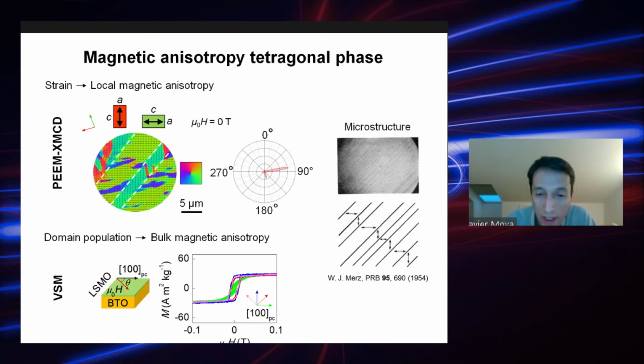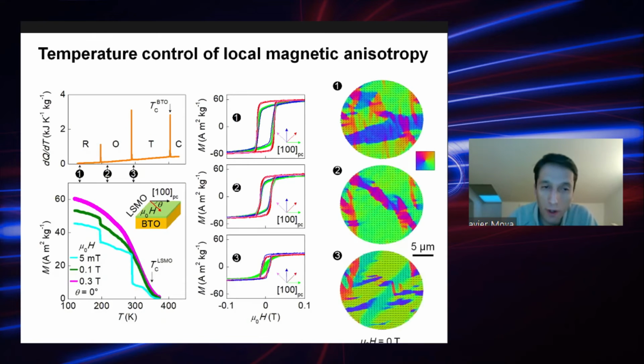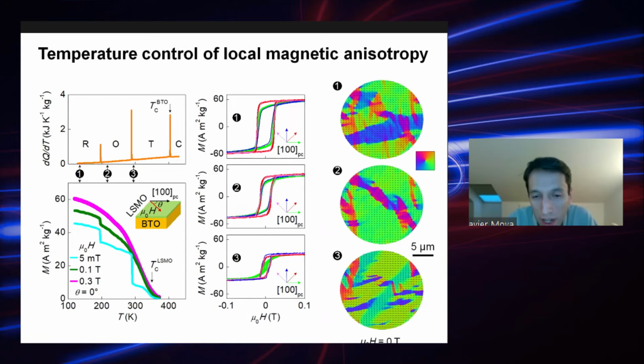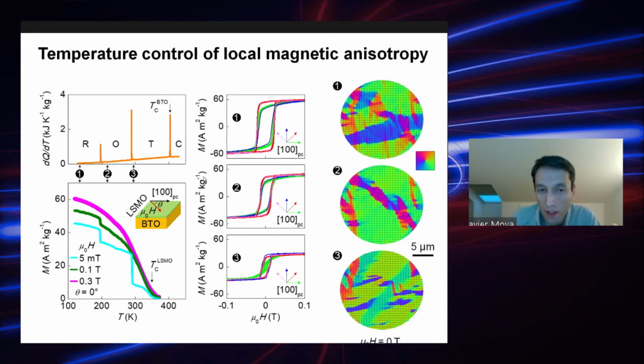So the question is then, can you manipulate this microstructure with an electric field in order to have magnetoelectric effects? And the answer is yes. So if you perform some magnetic studies again, here what we've done is measure magnetization as a function of angle at different temperatures in the different phases. So phase number 1 in this case is the rhombohedral phase, phase number 2 is the orthorhombic phase, and phase number 3 is the tetragonal phase.